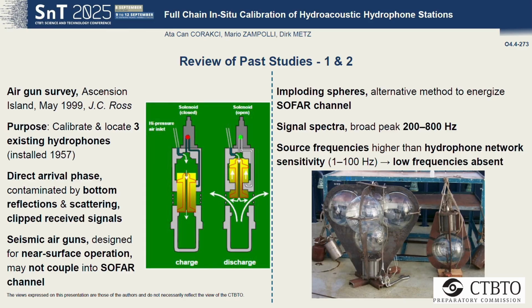Another study was carried out in 2000. Instead of air guns, imploding glass spheres were investigated as an alternative to air guns. And the issue in this exercise was that the spheres have a frequency response from 200 Hertz up to 800 Hertz, which is not the frequency band of the PTS.